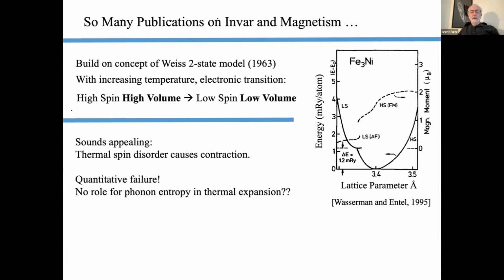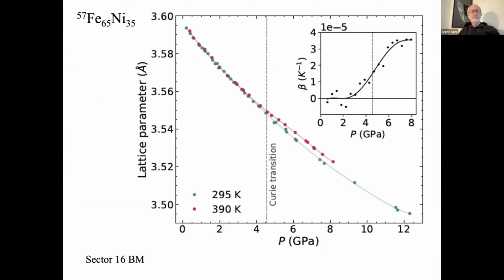But this has been a quantitative failure. Look how big these changes are. These are a few percent in the lattice parameter, which is not the scale of things. And there's no role for phonons in this. And this is something we've been looking at for other reasons. And usually we explain the thermal expansion by looking at anharmonic theory along with quasi-harmonic for comparison. This is really missing. It's surprising.